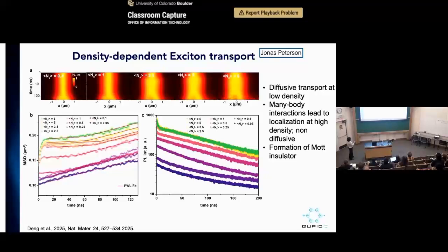And after tens of nanoseconds, some motion resumes. Also, if you look at the spatial distribution, initially you're going to see it just looks like a Gaussian-like distribution. At high density, you also start to see more of a pancake-like, square wave-like distribution.